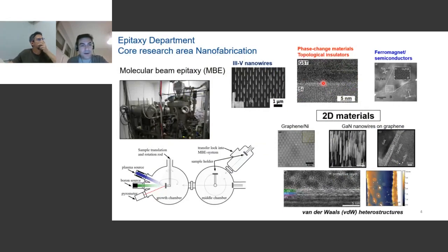The epitaxy department is mostly dealing with molecular beam epitaxy, MBE. For those who don't know, MBE is a system where you grow your samples, usually under an ultra-high vacuum regime. This is a picture of a typical MBE system at the PDI. You have your so-called growth chamber, which is under UHV, usually 10 to the minus 10, 10 to the minus 11 millibar pressures.